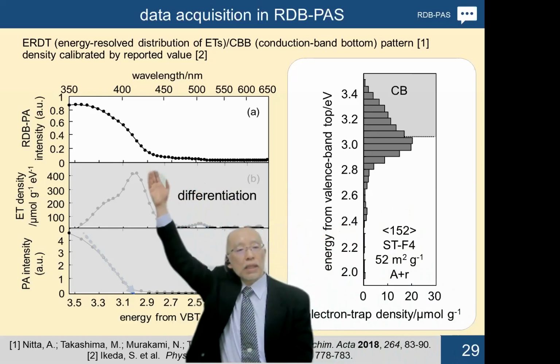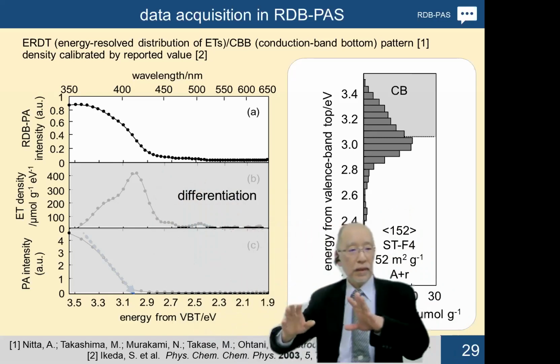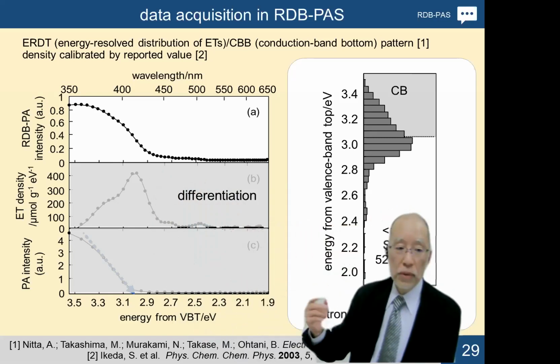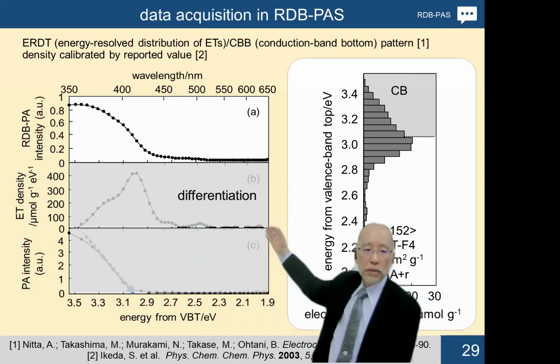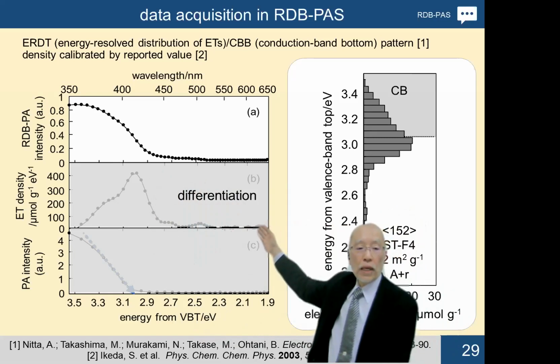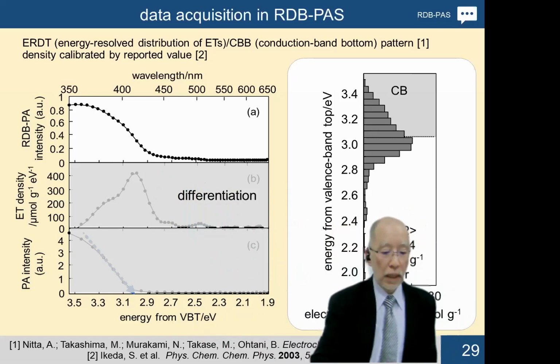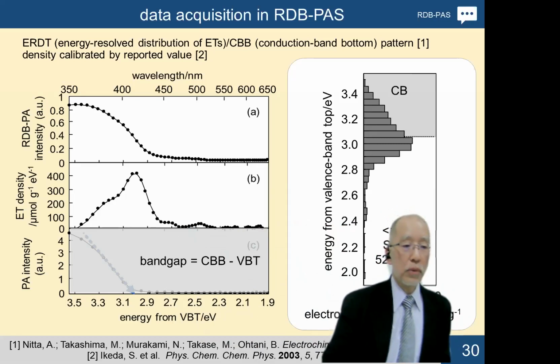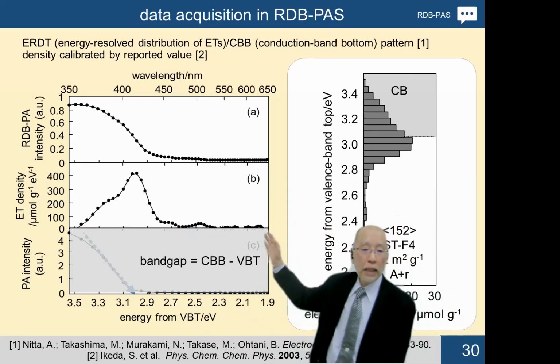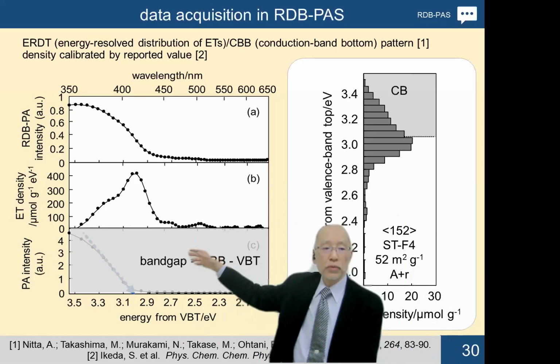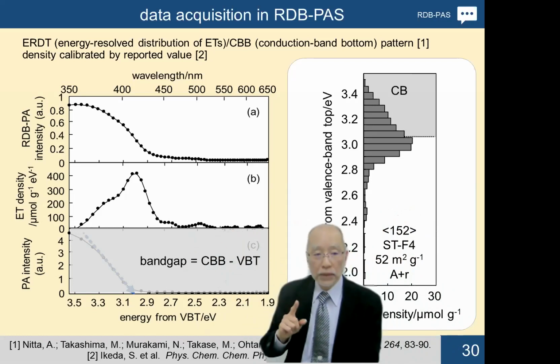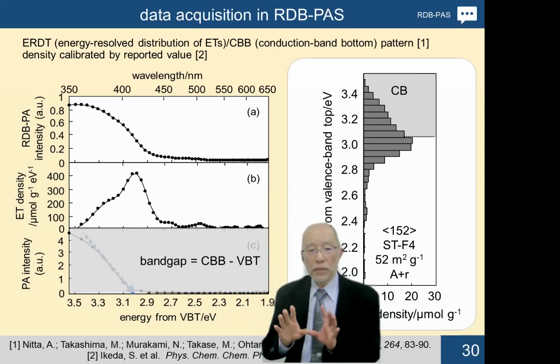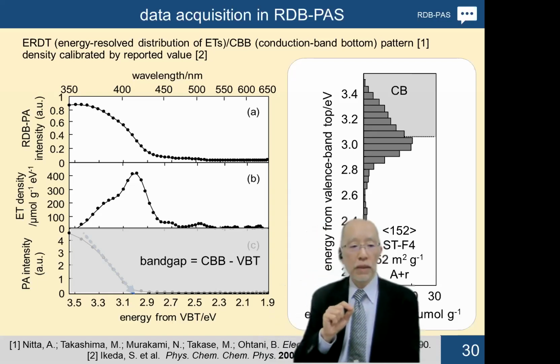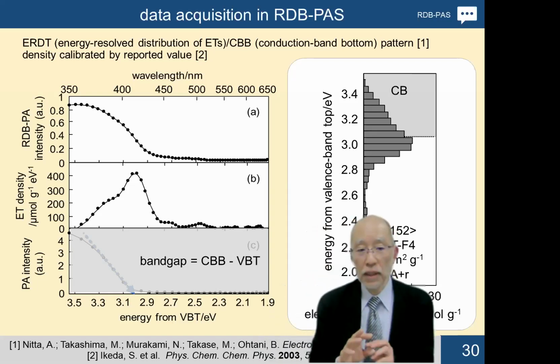And at the high energy part, that is much. And therefore, this is accumulation. So therefore, by differentiation from the lower energy side to higher energy side, it is possible to have the energy-resolved distribution of electron trap in relative value. So the important point is the PAS signal, photoacoustic signal, is just a relative value, no information of absolute photoabsorption.